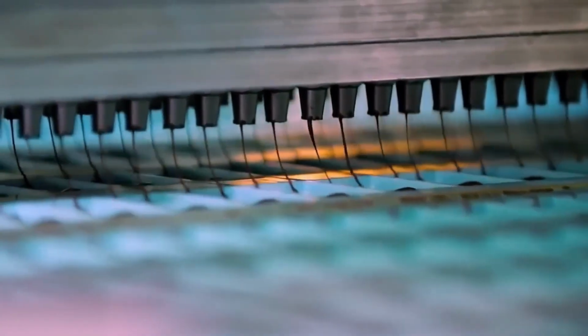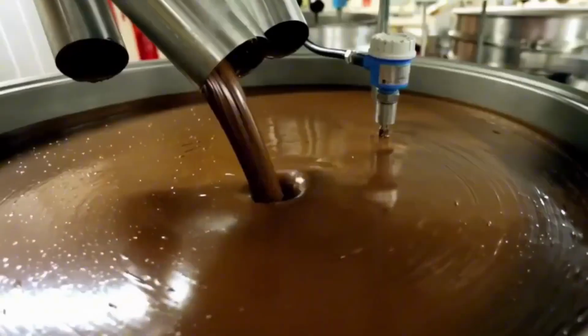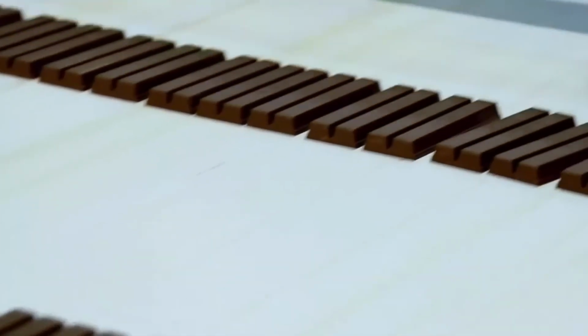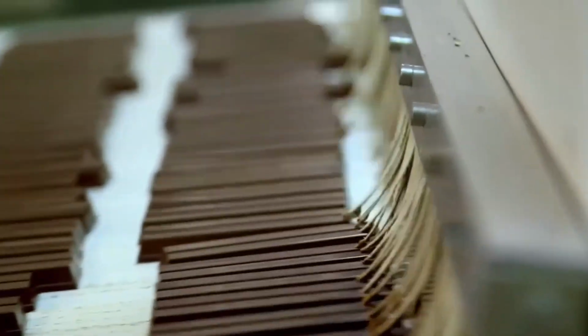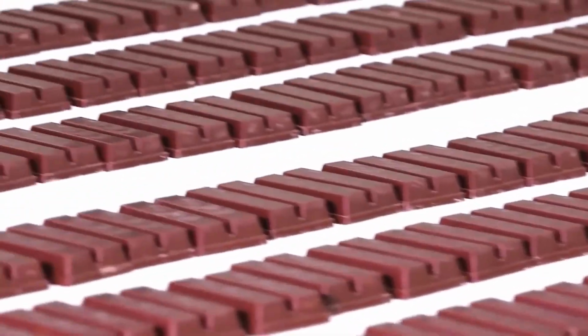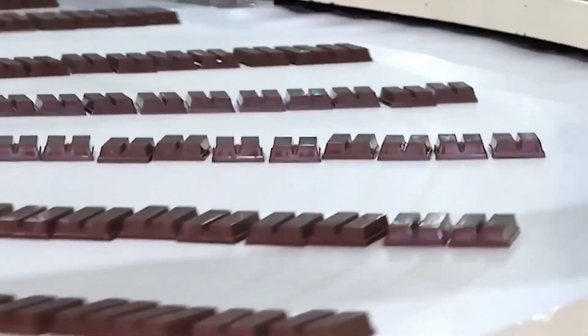A batch that exits tempering with the wrong crystal distribution will bloom within 24 to 48 hours. The surface turns white and matte as unstable fat migrates outward. That batch cannot be sold.